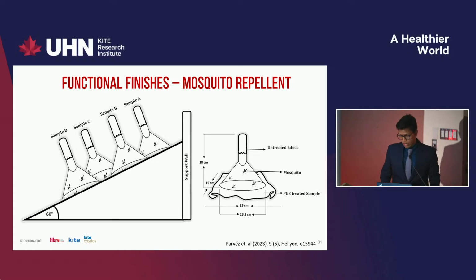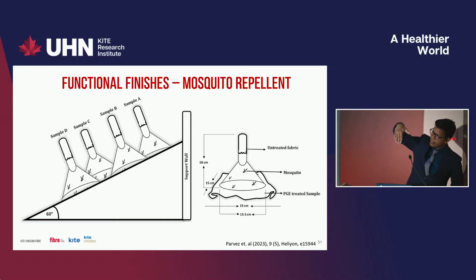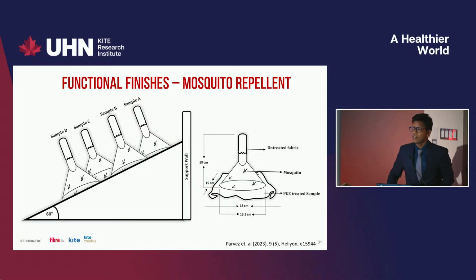For the cone test, the result we found was around 13.33% mortality rate after 60 minutes. And after 24 hours, we found up to 76.67% mortality rate of the mosquito. The way we do it, in the inclined area we put our samples, and then we keep the cone, and we inserted 24 mosquitoes, and then we cover the area which we use to insert the mosquitoes. We keep the mosquitoes in that cone exposed to the sample fabric. In our case, we kept it for 60 minutes. We counted, and then we did another test with 24 hours. And as I said, with 35% extract solution, we got the result of 76.67% mortality.